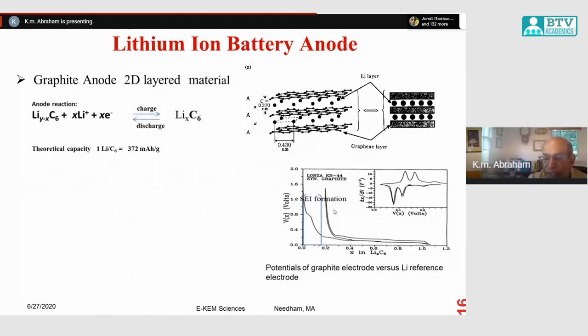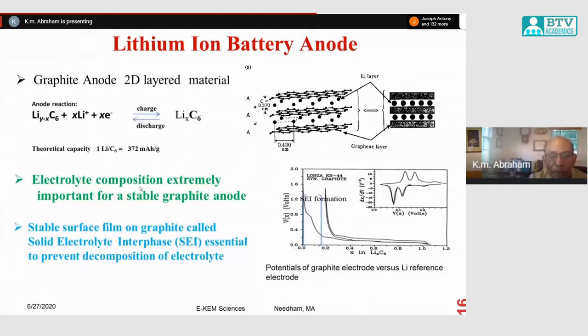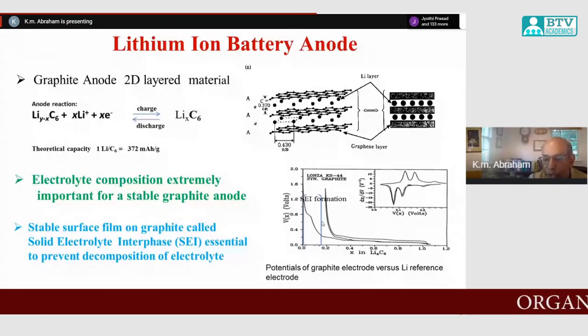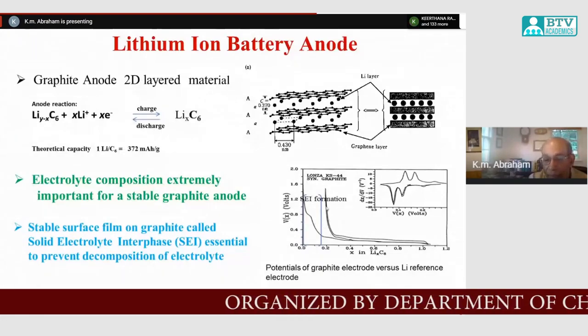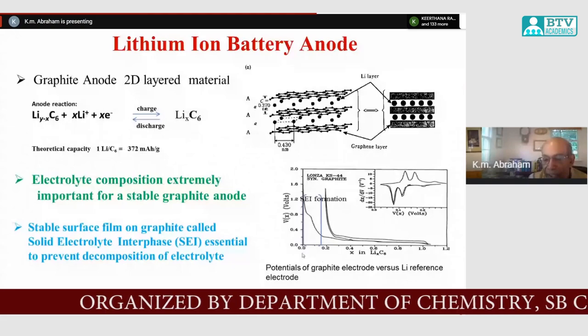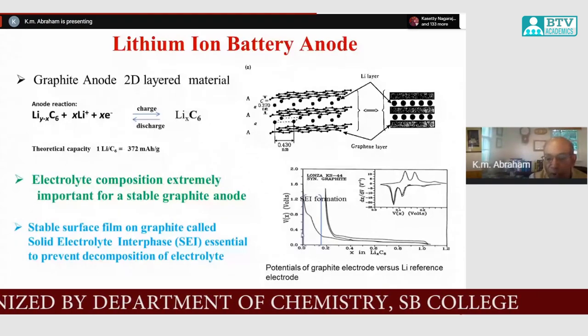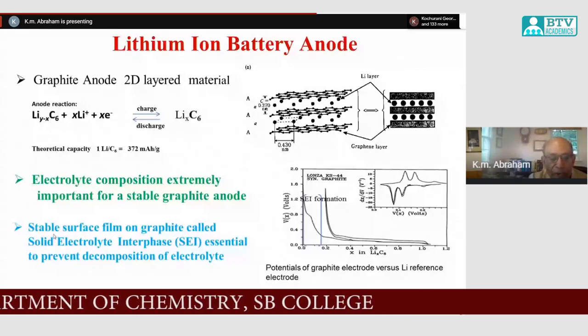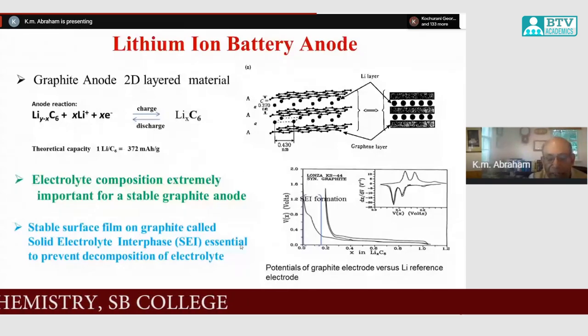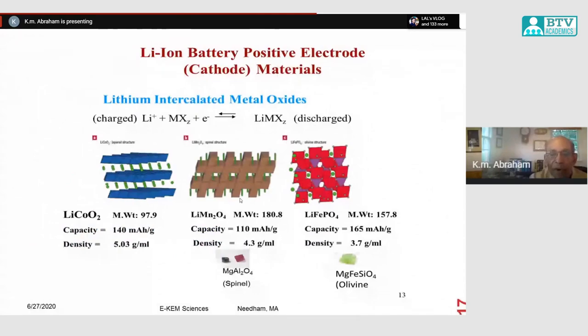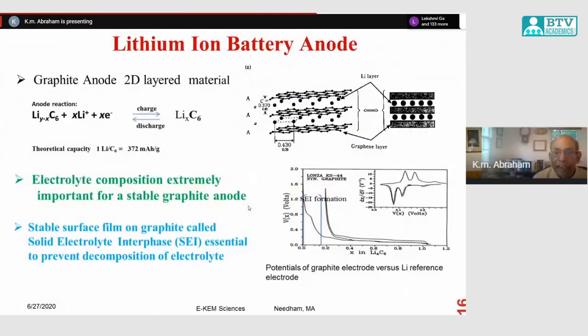So the formation of this is very important, and that depends upon the solvents that you use. Electrolyte composition is extremely important for a stable graphite anode, because you have to find an electrolyte that reduces to form an insoluble surface film that conducts ions. There's a lot of organic chemistry and surface science involved in that. So you have to have a stable surface film on graphite, called the solid electrolyte interface, essential to prevent decomposition of the electrolyte. So that is the chemistry of the graphite anode.